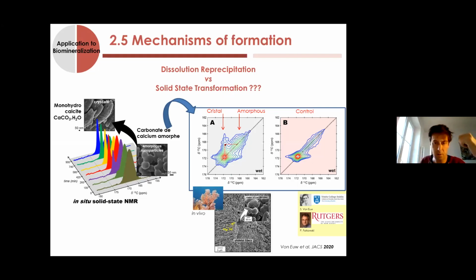By using spin diffusion experiments, when you probe the long distances, you see that the amorphous phase is in very strong and short contact with the crystalline phase, through the observation of an extra peak off the diagonal. If you use a control, meaning a mixture of crystalline and amorphous phases but randomly distributed, you don't see that specific extra peak. So that's really the proof of a solid state transformation occurring in vivo in the case of corals.